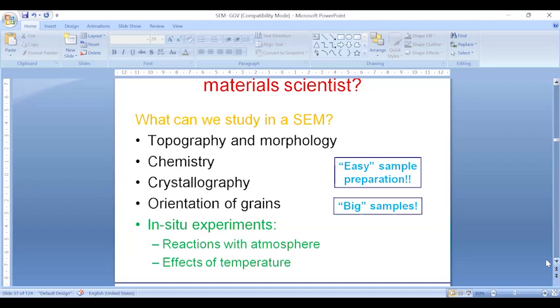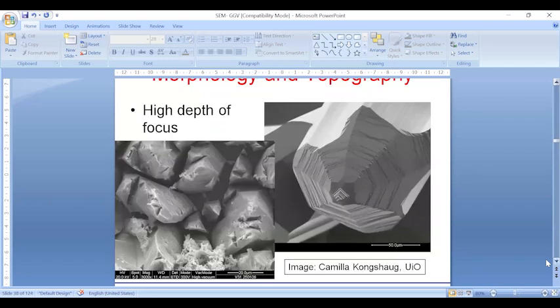So basically in a SEM it is very easy to prepare your sample, and you can use a sample nearly inches in size, but in a TEM you can use your sample only less than 100 nanometer. That is one of the bigger differences between both instruments. And also topography and morphology, that is the qualitative and quantitative things. And the most important thing, the depth of focus is very high compared to optical microscopy and any type of microscopy available in the market.